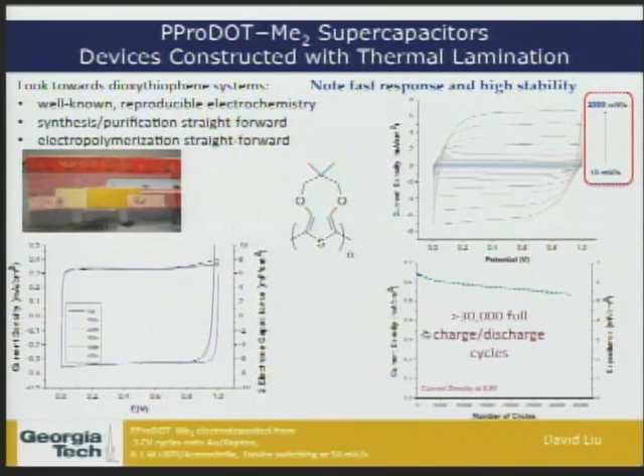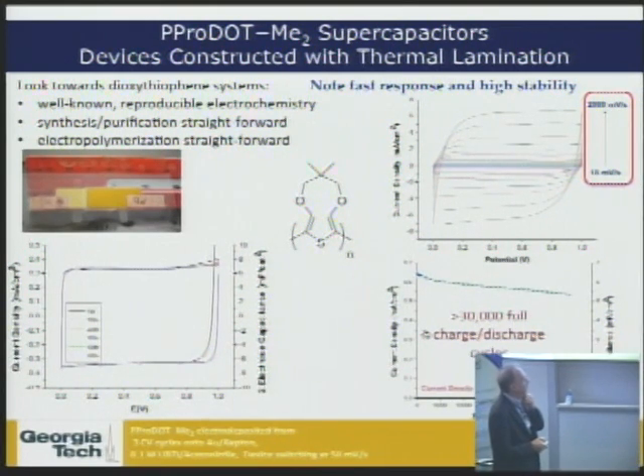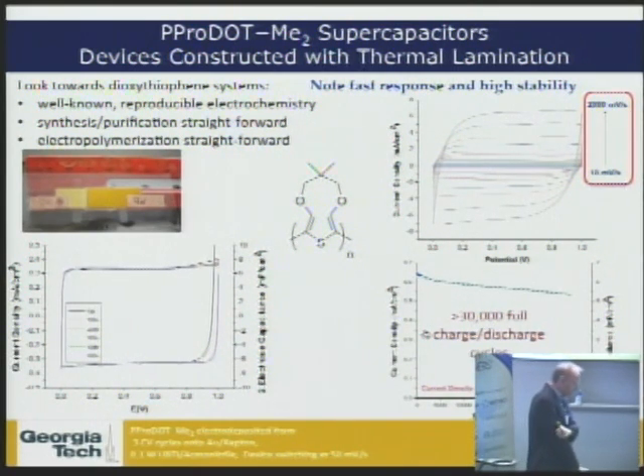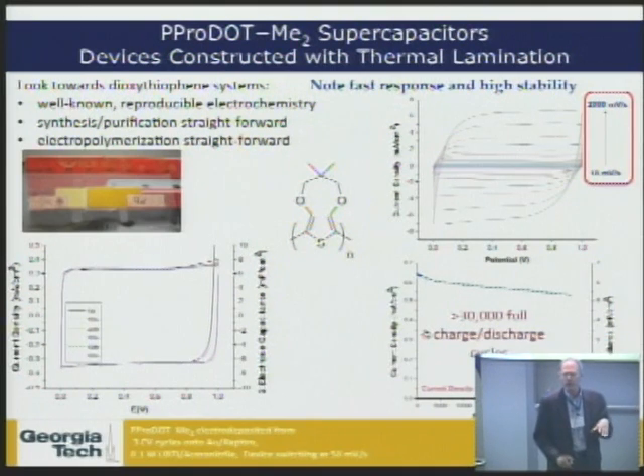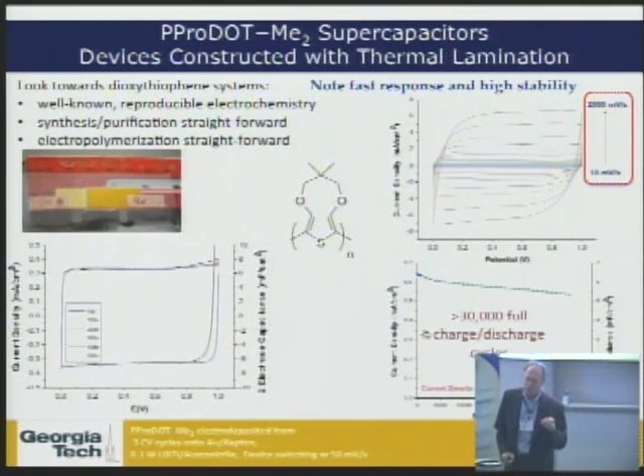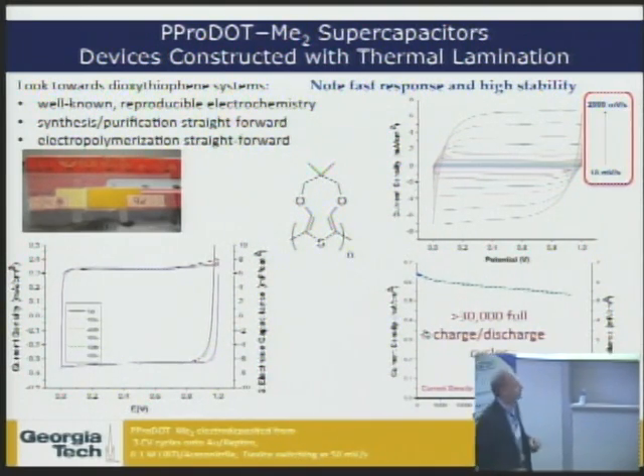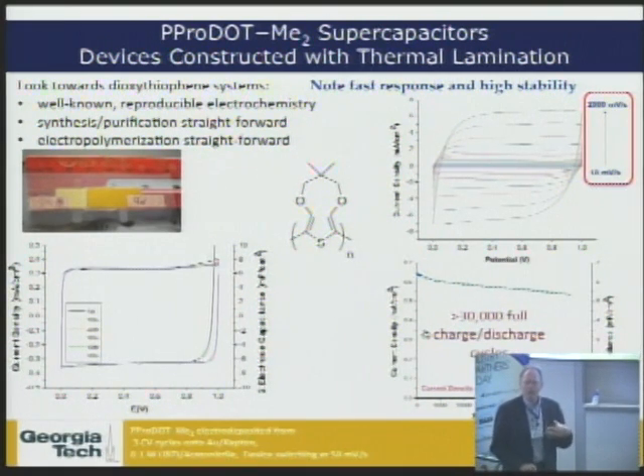supercapacitor, in essence, that we've built using this dimethyl propylene dioxythiophene polymer. And a couple things that I want to point out here. First off is the overall capacitance of these systems. Electroactive polymers and composite materials can attain capacitances on the order of 200 to 500 farads per gram. And so there's a significant amount of capacitance that is obtained because they are conducting, they have very open morphologies. Ions penetrate rapidly in and out of the system. And so you end up with a relatively high level of capacitance.